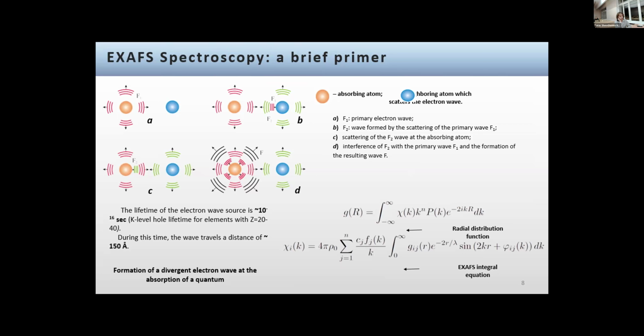This method utilizes the process of when the sample gets illuminated by an X-ray, the atom under study emits a photoelectron, and you get an absorption peak. But this photoelectron actually can interfere after the absorption with the neighboring atoms and, having, of course, wave-like properties, scatter back to the original atom and disrupt its electronic structure in a way. And as a result, we see the oscillation in the absorption spectrum appearing. And these oscillations are actually modulated by the spatial distribution of the neighboring atoms. And this is how you actually may get insight into the local atomic environment around a certain specific atom, even if your structure is disordered.